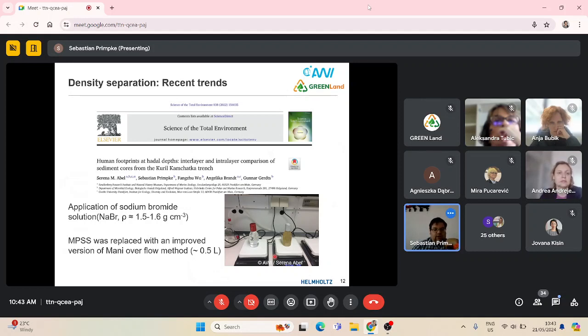hypersaline solution. At the time, we had the issue that zinc chloride is not optimal. It has an environmental hazard, and we switched to sodium bromide, which is considered less harmful, depending on which safety data sheet you look at. But it has worked out quite well. It has a better viscosity, so it's easier to filter. And we also changed the bottles a little bit. So we now have straight-neck bottles, so-called Nalgene filtration bottles, which are even more effective than the Erlenmeyer flask for overflow, and we can simply reuse them several times and can run this process up to 6 times in a row.